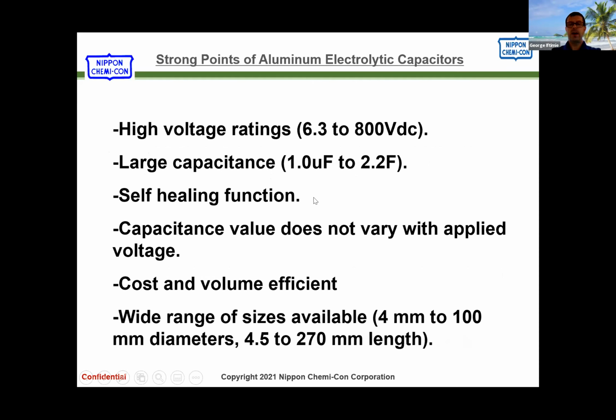Hybrids also have it. Polymers technically should have it, but basically what we mean by self-healing is the aluminum oxide gets damaged during application, and it gets damaged by ripple current, temperature, and various factors. So if you don't do anything about it, you will eventually have an ever decreasing thickness of the aluminum oxide, and a lower voltage, quote unquote, resistance of that aluminum oxide. Self-healing will essentially form new aluminum oxide to heal the cracks.